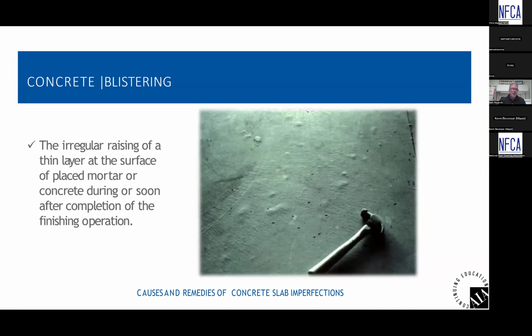Blistering. With any type of concrete or mortar material, if the finishing process happens too quickly, you can trap air right at the surface of the concrete that creates a blister. So this is a picture of a concrete slab that has blisters in it. You can see the raised blisters. And it's a function of the troweling of concrete. If we close the surface of fresh concrete before it's hard enough and ready enough to have a steel trowel on it, we can trap air within the surface of the concrete that equates to a void at the surface and a blister when it's all said and done.